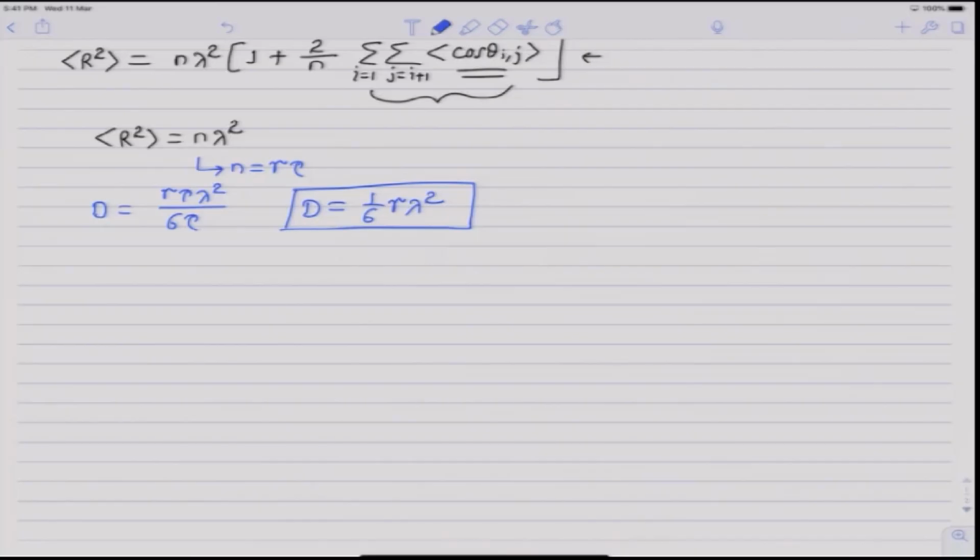And second, the next site or one of the nearest neighbor sites has to be vacant, so that the atom can jump onto that site. When these two conditions are satisfied, a particular vibration will convert into a successful jump. So, we can write gamma as nu 0 exponential minus delta G m by RT times X 1v.